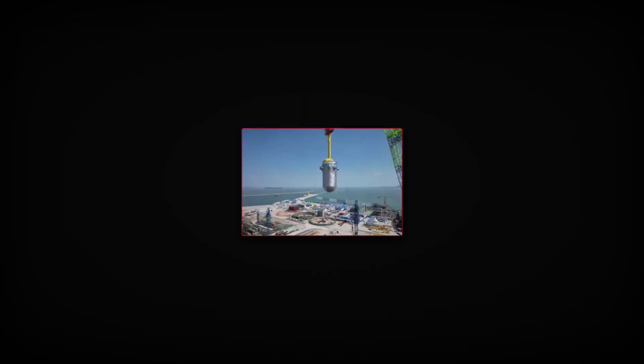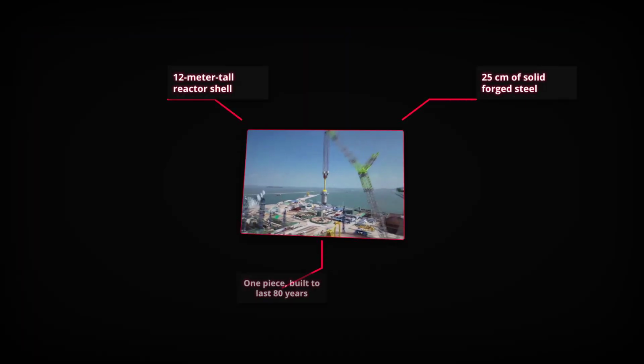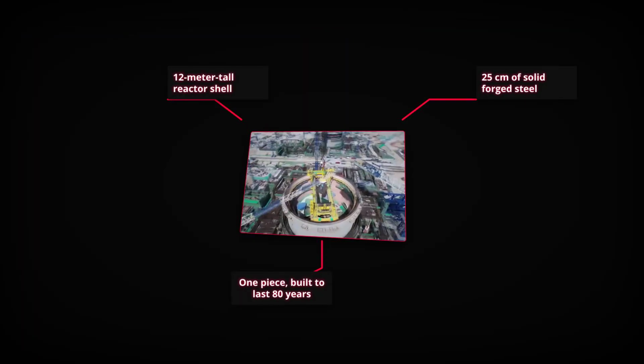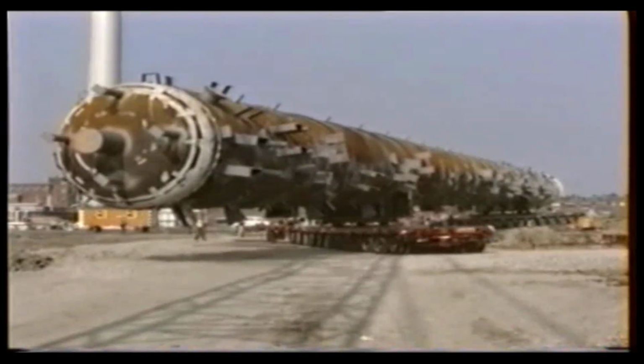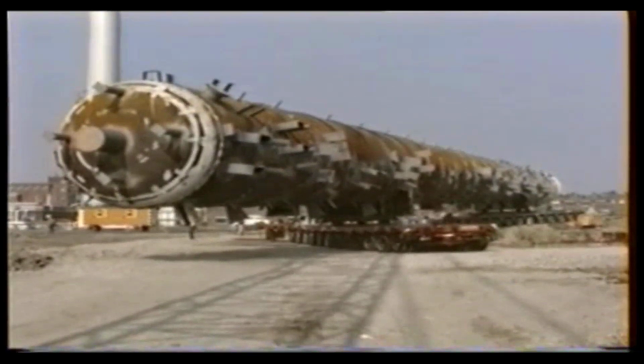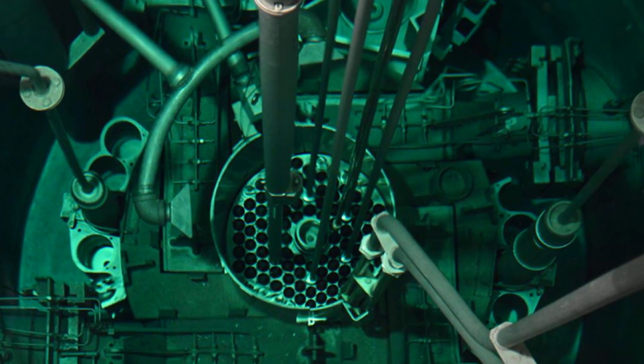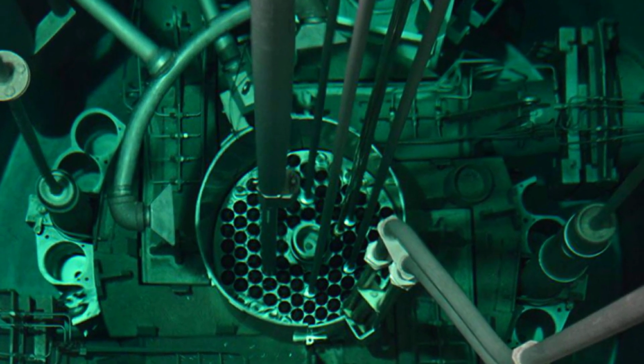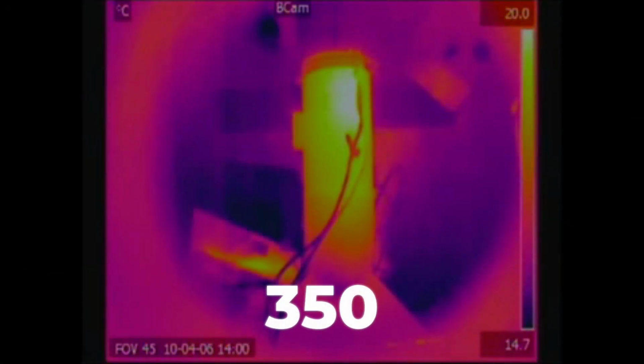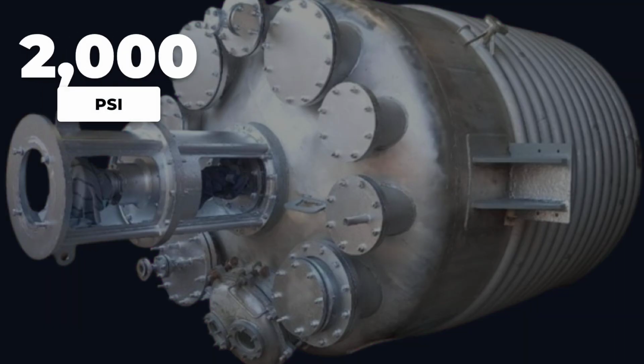Picture a cylindrical steel container standing 12 meters high with walls up to 25 centimeters thick, weighing somewhere between 320 and 500 tons when complete. These vessels house the reactor core, the coolant, and the control mechanisms, operating at temperatures between 300 and 350 degrees Celsius under pressures reaching 2,000 pounds per square inch.